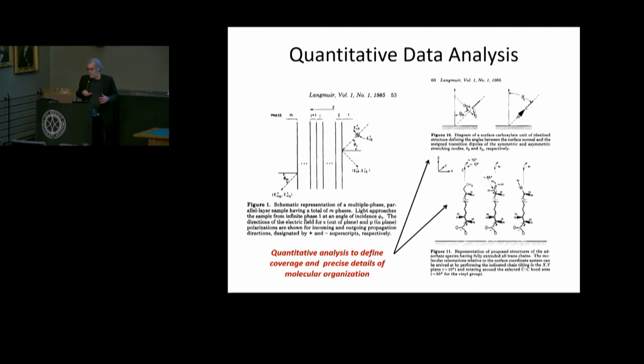It's in deprotonated form, etc. And then we start talking about things related to how the bonding group directs the chain, how the chain assembles to pack hydrocarbon to hydrocarbon, in a self-association, and ultimately what winds up to be the projection of the functional group at the ambient interface. And you notice that the functional groups shown in this model case are ones that don't perturb bonding of the head group, right? Because you can't be polar in this case because the underlying substrate is polar.